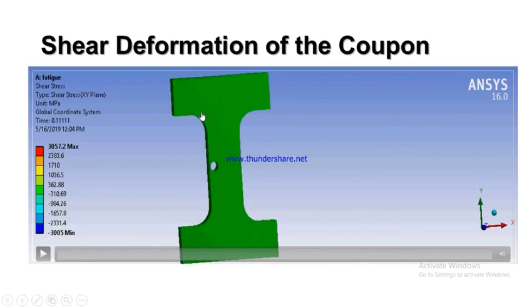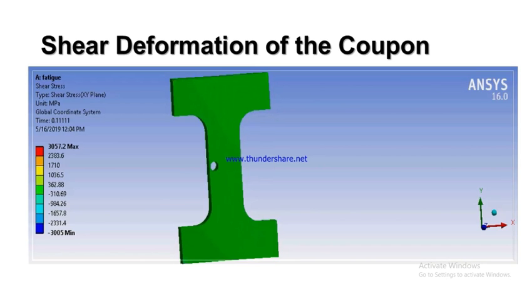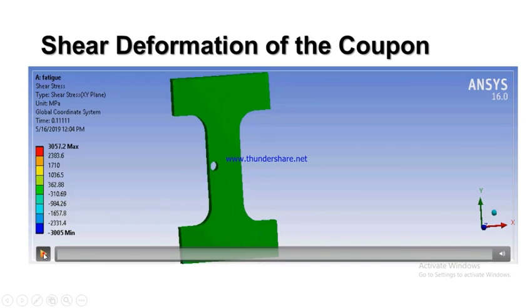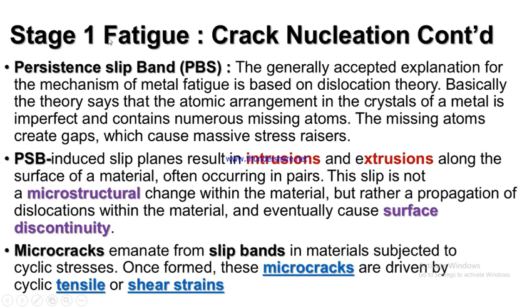Initially, when we simulated this particular coupon, we found that the stresses were concentrated at the fillet parts of this system, which has to do with the discontinuities in the system. But when we incorporate a notch into it, all the stresses migrated to the notch, because the notch is acting as a stress riser.